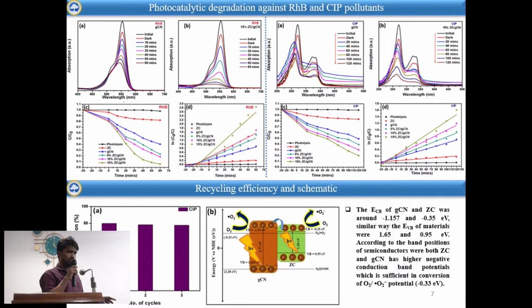And we have also carried out the recycling process for the highest-level sample for the CIP pollutant. We can see that there are some minor reductions in the degradation percentage. We can conclude this is due to material loss, because once we use that particular material again, we have to do a drying process, and there will be some loss of material. Due to that, we have obtained some variation in the degradation percentage over the 3 cycles.